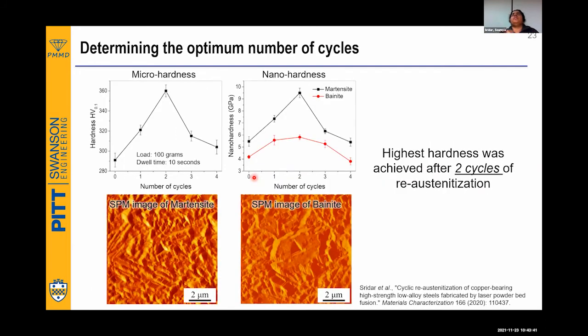So this is a typical introduction to quenching dilatometry, but our purpose is not that. I want to figure out the number of cycles which is optimum. So we did two things. One is finding the microhardness, and we find a sudden increase in hardness at 2 cycles. And then, what's going on? We do nano hardness, using nano indentation.